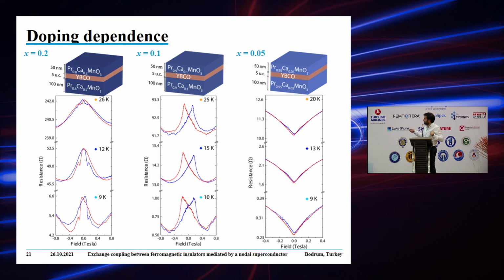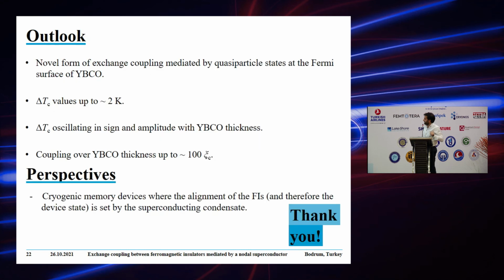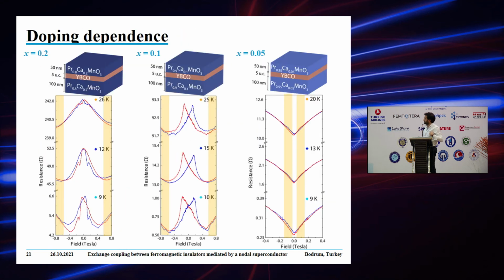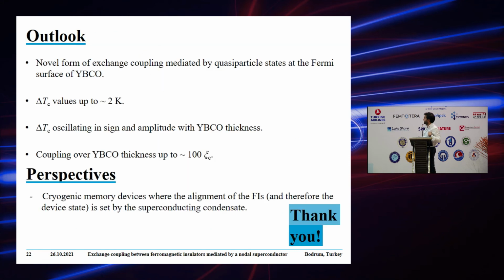So I reduced the doping, and in this case, as you can see, you go from a state where the parallel state is favored to a state, at low doping, where the anti-parallel state is instead favored. I think the pointer is behaving very funny. Okay. Anyway, the outlook is that we proved this nodal exchange coupling is possible